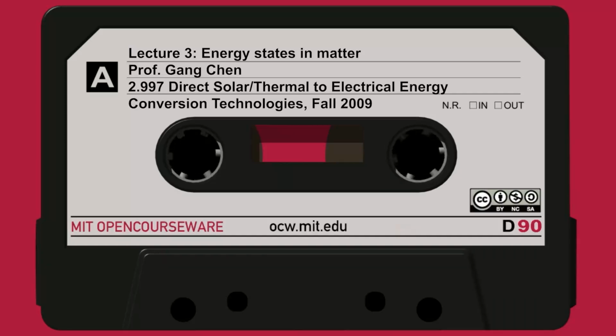It's the trick you do all the time in counting the numbers in crystal. You convert the number of states summation into integration. You choose your integration variable either in energy or wave vector. And if I group everything all together, this is my F, and this one I call the density of states.